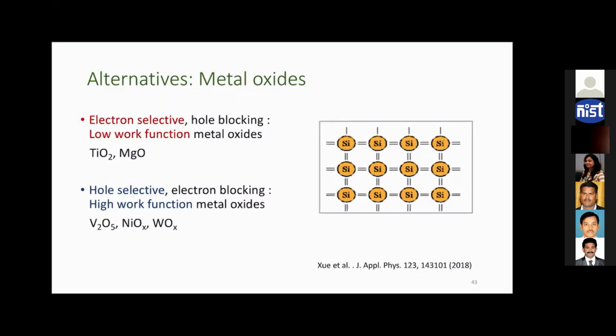And once this interface surface bond breaks, it again becomes an electrically active trapping site. So, in short, amorphous materials are always helpful in good passivation because they can relax their structure. So these metal oxides, being oxide and amorphous, are very useful in passivation, but you have to make sure that these metal oxides are amorphous in nature.